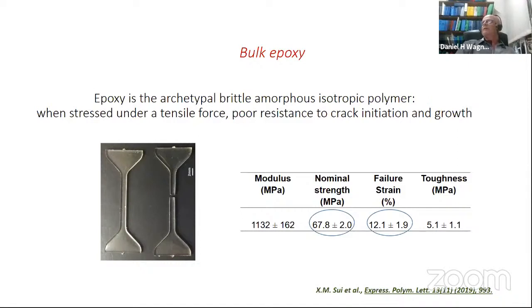Under tensile force, there is poor resistance to crack initiation. This is epoxy. This is how it looks. This is how the break looks. And the nominal strength typically is around 70 megapascal, while the failure strain, you can play with the failure strain, but it's usually somewhere between 6 and 12%. And the toughness here is 5.1, but that's less relevant at this point. I want you to remember this value here, and the modulus is 1.1, 1.2 gigapascal usually. But the 70 megapascal here is important, and 12% failure strain is also important to remember. So this is a typical failure of epoxy.